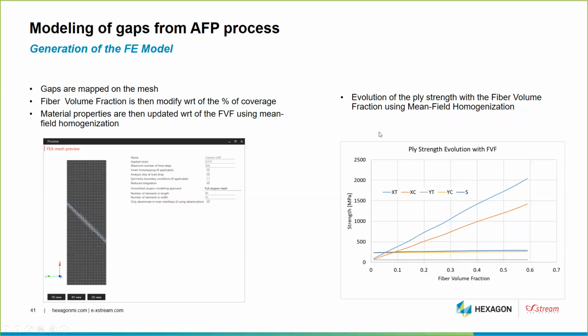Here you have an illustration of the evolution of the ply strength with the fiber volume fraction, using mean field homogenization, from 60% of fiber to the pure resin. You see the evolution of the axial strength, for example in tension and in compression, and the transverse one. It's not so clear on the transverse one, but on the axial one, it's very clear.